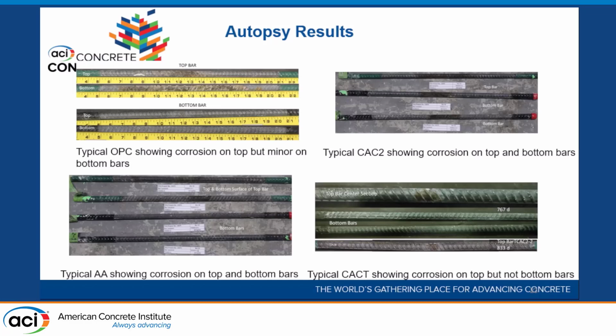It's not measuring what's going on locally on the samples. So you can see on the control sample, there's corrosion on the top, but the bottom bars are pretty clean. The CAC2, which was aluminate, you see you got a fair amount of corrosion on the bottom bar as well as the top bar, indicating that that's going to take away from your macrocell. If you have a bottom bar corroding, it doesn't send any cathode current up to the top bar. And we have the same thing occurring on AA1 to a little less extent, some corrosion on the bottom bars.